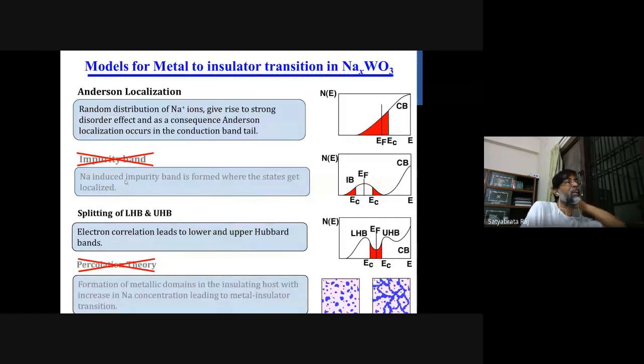Now we have discussed the impurity band. We are left with the Mott transition and the Anderson localization. The Mott transition is very unlikely because the tungsten 5d bandwidth is quite large, and for any small amount of sodium doping, even 2.5 percent, the sample is still insulating. The Mott transition should be valid when X has to be integral, so that the band is half filled, and then only the Mott criterion will be applicable.